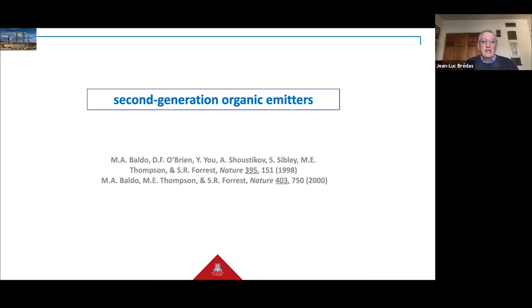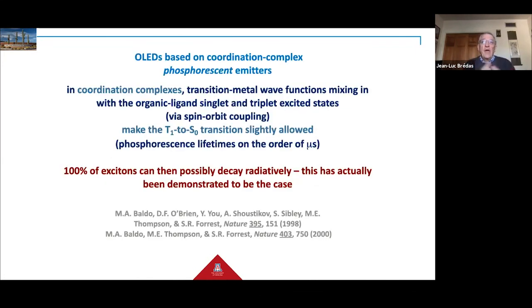And so in the late 1990s, Mark Baldo, Mark Thompson, and Steve Forrest designed the second generation of organic emitters, which are based on coordination complexes that have heavy metal atoms at their centers. And in those coordination complexes, because of spin-orbit coupling with the heavy transition metal atom wave functions, the transition from the triplet states down to the singlet ground state becomes allowed. And in those instances, 100% of excitons can possibly decay radiatively, and that's actually been demonstrated to be the case.